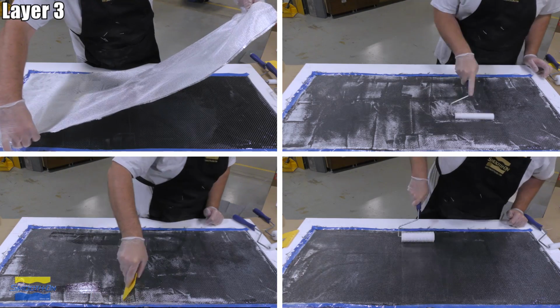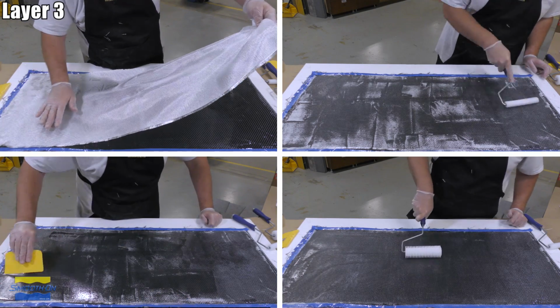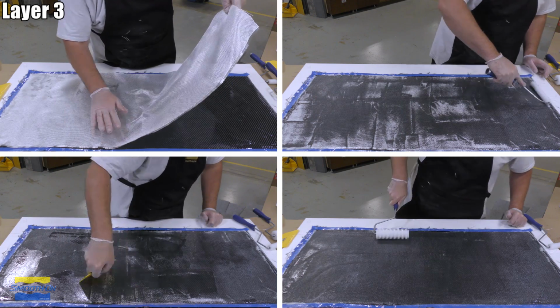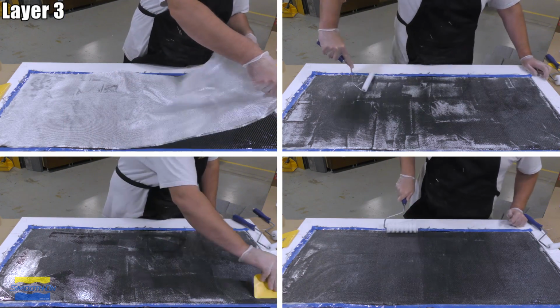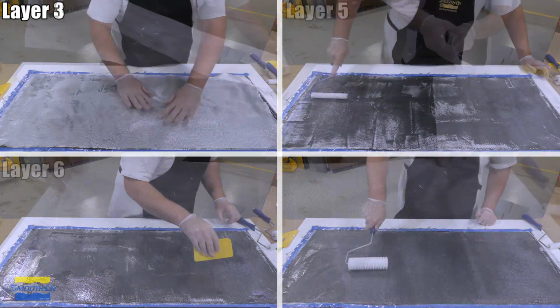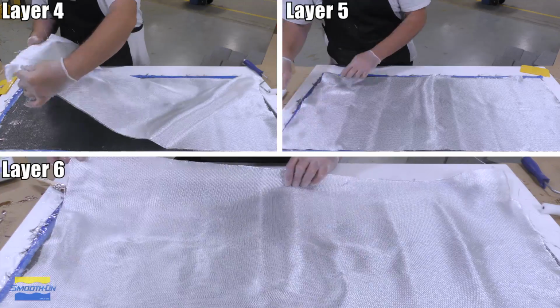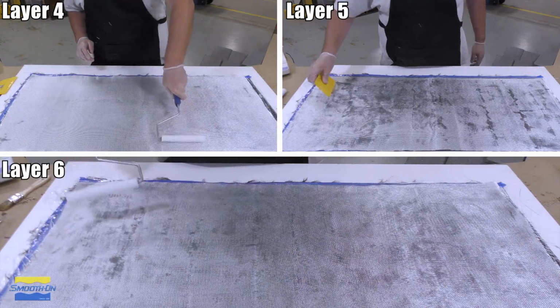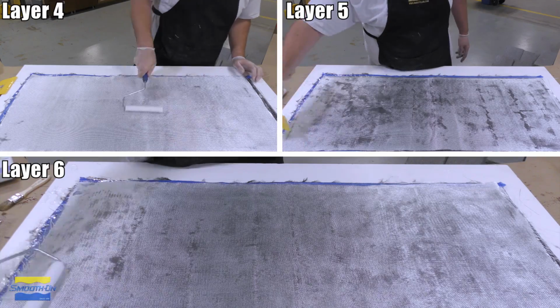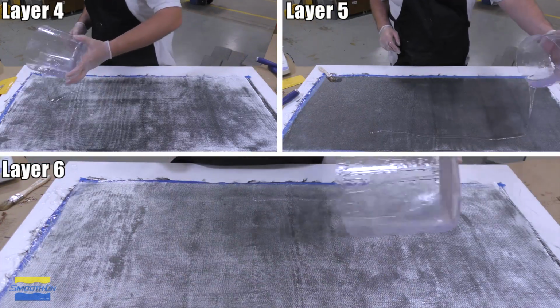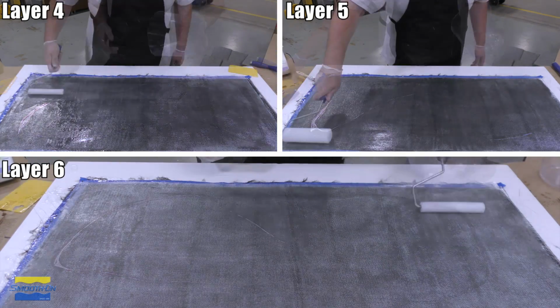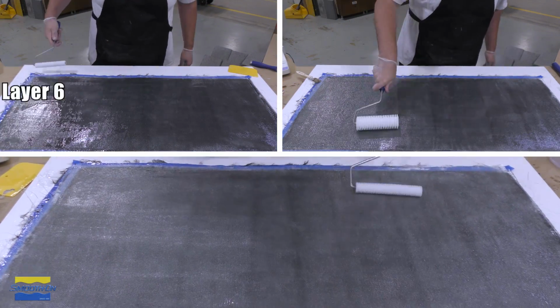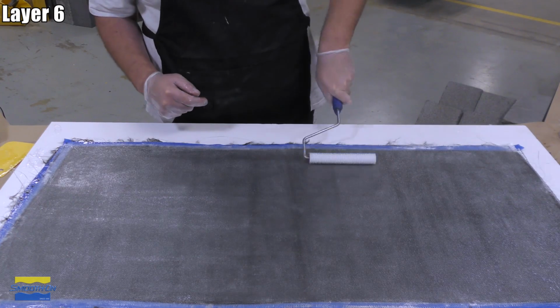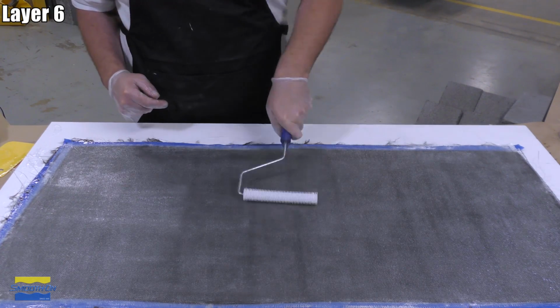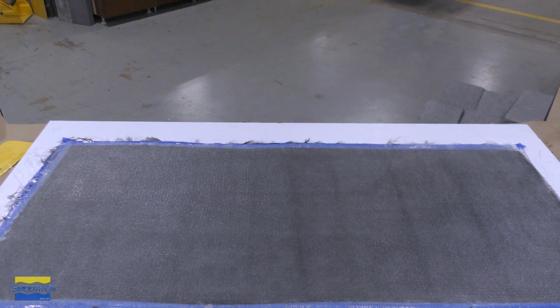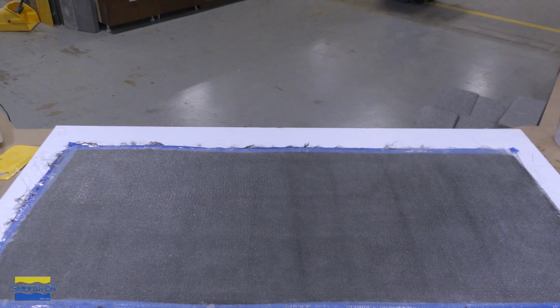Now this procedure is repeated until all the glass fiber cloth is used up. I have 4 layers of the glass fiber cloth and 2 layers of the carbon cloth here. It gives us a total of about 3 millimeter thickness, and that's exactly what I was aiming for. And again, at the end you want to make sure that you roll out the epoxy to make sure that it pops any of the bubbles that might be still present in the material, and also to spread the material as evenly as possible throughout the whole layup. This entire layup is now allowed a full cure of 24 hours.